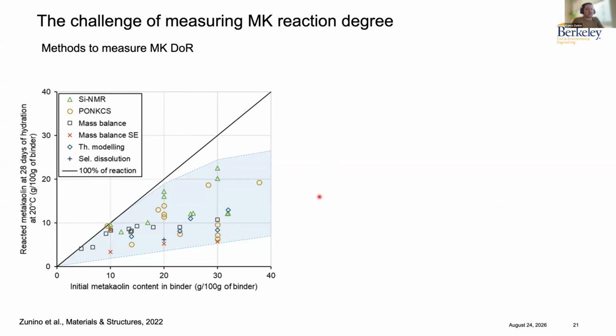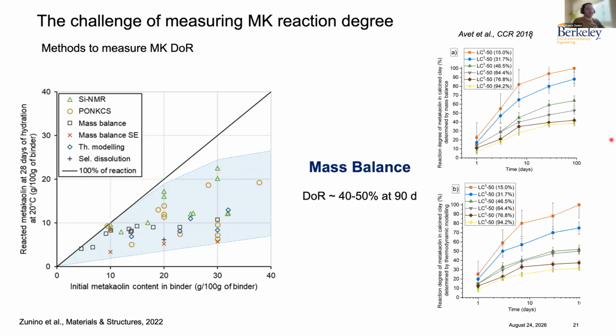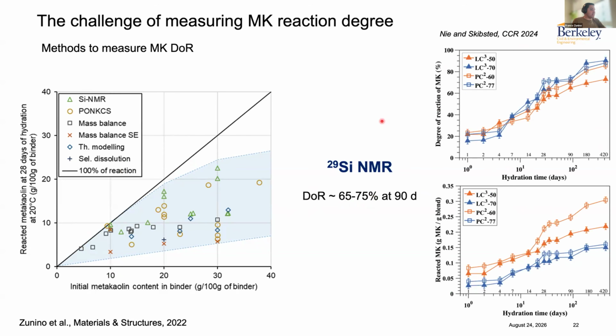So the problem here is that measuring the degree of reaction of an amorphous material like metakaolin is challenging, and there are several ways of doing it, and all of them have disadvantages. So this is a paper we published in 2022 using a methodology called mass balance, and when we use mass balance, we obtain for different clays that we sampled a degree of reaction of 40 to 50% at 90 days. The other way of doing this is by 29 silicon nuclear magnetic resonance. So this is a methodology pioneered by the group of Jørgen Skibsted in Denmark. And with that technique, we obtain about 65 to 75% degree of reaction. So actually higher than mass balance. And we think that the reason for that has to do with the signal to noise ratio in those experiments. It's actually quite difficult to detect the metakaolin after the degree of reaction has evolved beyond, let's say, 50%.